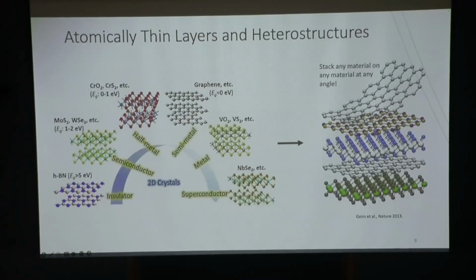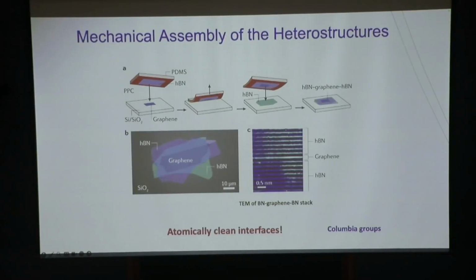Depending on what you want to study, you can combine different pieces to make different types of heterostructures. Initially, when people drew this, a lot of people thought it was just a wishful-thinking cartoon. But researchers did try. They actually just used a relatively simple plastic stamp. After you exfoliate the monolayer or few layers, they can pick up a piece of boron nitride, pick up a piece of graphene, and pick up another boron nitride. So you can really stack them like atomic Lego. And the most important thing is these Legos are of very high quality.